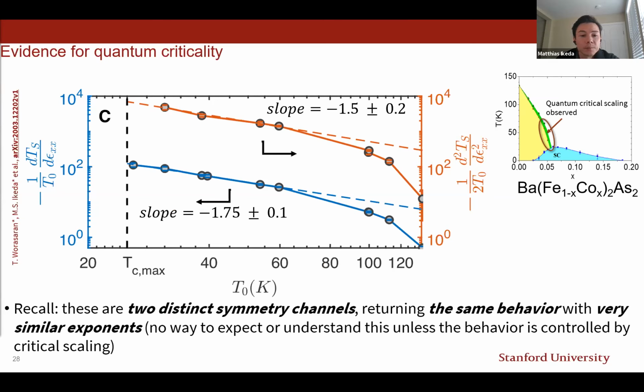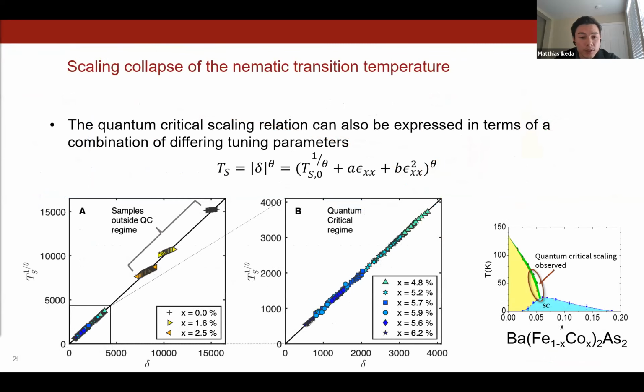barium iron cobalt arsenide. The same data is even more impressive if we now take a look at the transition temperatures themselves, and not only at the linear and quadratic coefficient of the nematic phase transition. And we plot this now against a combined tuning parameter that now includes the linear strains, but also the quadratic strains. And we can see that we indeed observe a perfect linear scaling relation for all materials showing cobalt concentration of 4.8% or higher.